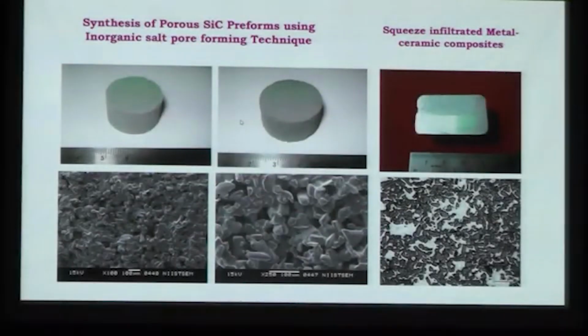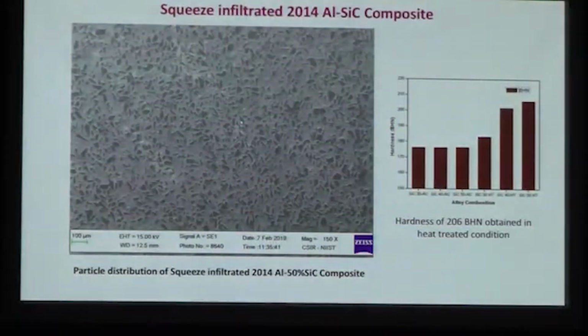So this is what I told you, a porous preform, and once you pour the metal and squeeze infiltrate, we will get a composite like this. Here we can see a high volume fraction of silicon carbide particles infiltrated with liquid aluminum metal. This concept can be used to make thermal management plates, which require low CTE and high thermal conductivity. Normally we know that aluminum alloys have very good thermal conductivity, and copper has even better, but the problem is the CTE of these alloys is very high. For any electronic component, the CTE has to be below 10 ppm per degree C or per Kelvin. So we used this concept to make it.